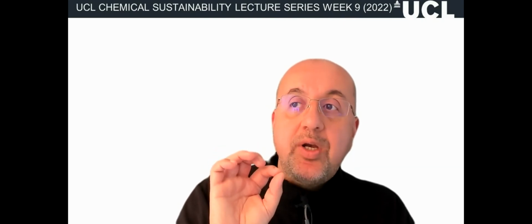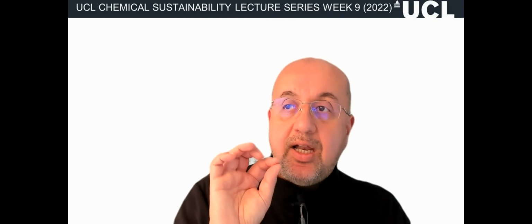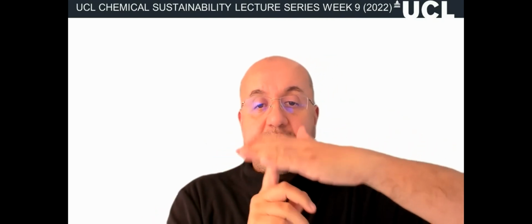So the nice thing about certain things that you can put on the surface, they can form a lithiated species, which kind of acts as a reservoir for lithium and a sort of protection as well. So zirconia is one of those elements. You can form lithiated species, but of course we're not coating. So what we are doing is doping, and it goes back to what I said about the layered structure. What some people believe is that the zirconia, because it's not electroactive, will just stay where it is, and it acts in a sort of pillaring, if you've got these sheets, as pillars to stop the sheets from breaking apart or from degrading. Because often what happens is that process will lead to the formation of rock salt, which is less electroactive.